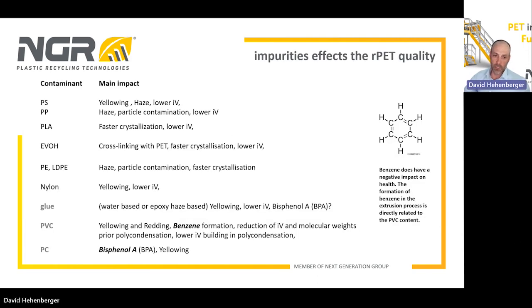I would like to start with the impurity effects on the rPET quality. When you take a look at the first contaminants like polystyrene, polypropylene, PLA, EVOH, PE, LDPE, and nylon, these types mainly have an impact on the color, on yellowing. Another impact is a faster IV drop in the extruder, and they lower the IV increase in the polycondensation process. Some of this also leads to a haze effect, to a discoloration. But these contaminants do not have an influence on health, so it's more a mechanical and property issue.